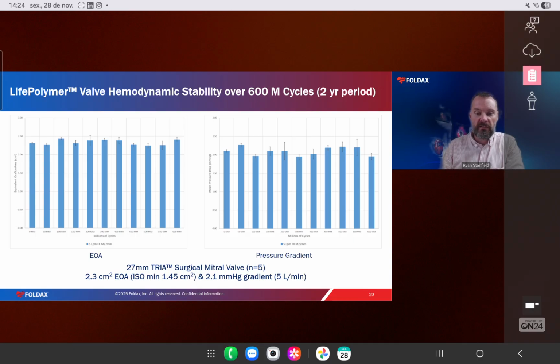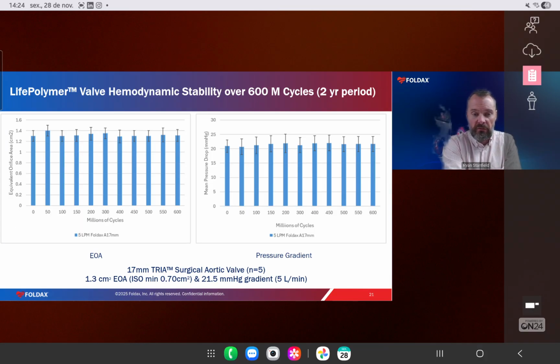And this test, at accelerated, takes about 2 years, and it simulates almost 20 years, depending on how you do your math, 16, 17 years of real-time use. And so you can see here that the effective orifice area is stable over time, the pressure gradient stable over time. We also do this with our small aortic valve. So same thing here. This is a different size valve, but it's very stable over time in in vitro testing under accelerated wear conditions.